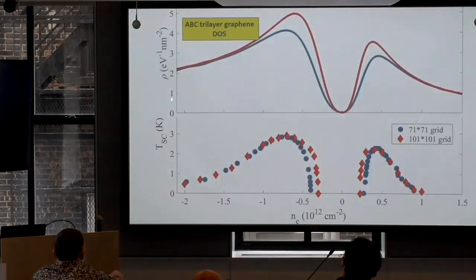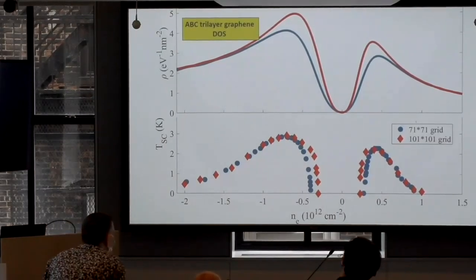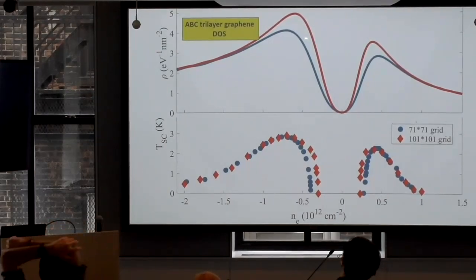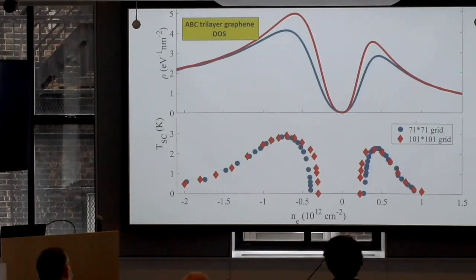So this is the density of states. Now do a Tc calculation. This is the self-consistent BCS, and you can see that Van Hove is where the superconductivity peaks, but it doesn't disappear right away. So the argument that there is superconductivity far away from Van Hove, so it cannot be electron phonon, is just incorrect. This depends a little bit on the grid. Yang is very careful, and it has converged but not completely. But I was happy publishing this. And so this is the result.